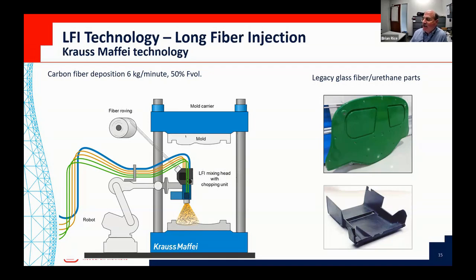We want carbon fiber, we want a high Tg urethane, we want 50% fiber volume, no porosity, for the strength and stiffness. So that's what we're doing on this program now, is spraying up carbon fiber with the urethane, and we're going through a different evaluation of candidate carbon fiber tows, and looking at different spray up patterns and so forth and so on. Later on, we have an interest to do a hybrid approach where you could take a continuous fiber preform, lay it in the tool, spray up your chop. We're going to have buildup areas, and then mold it. So very much it'd be like thermoplastic overmolding, but this is with a thermosetting snap cure urethane. And a pretty impressive deposition rate, about 6 kilograms per minute. So it's a pretty fast process.